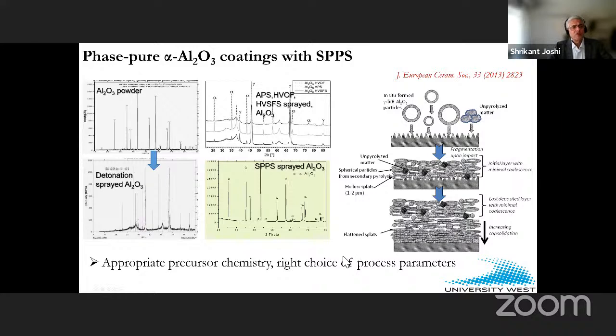When it comes to wear, one of our earliest efforts was on alumina, because in a sense that's a low-hanging fruit. If you want to spray nitrates or citrates of aluminum and try and get in situ formation of alumina. What was interesting, however, was the ability to get phase pure alpha alumina if you sprayed it right. And this is not exploited enough, but there is great promise there, because as several of you who have tried to spray alumina powder using whatever route, could be HVOF, could be detonation, could be plasma, even if you start with phase pure alpha alumina, you don't get alpha alumina in the coating, right?